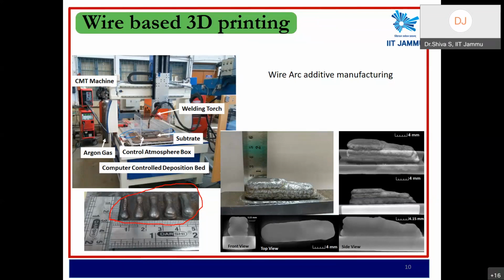So in case of 3D printing, in this particular CMT based technique, what happens in conventional welding, MIG or TIG, is that you cannot control the excess amount of heat, because the moment the arc ignites and sustains for a while, the temperature will shoot up, even to the point it can melt tungsten. It will go beyond 2800 to 3000 degrees Celsius. This enormous heat wastage can be restricted using cold metal transfer.